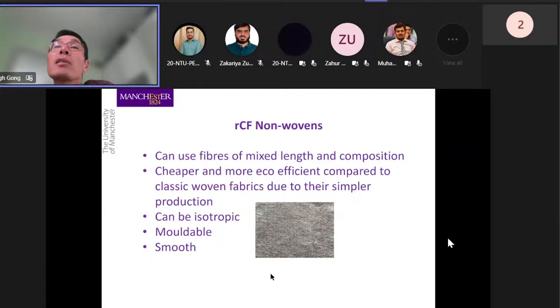And the processes of nonwovens tend to be much cheaper compared with traditional textile processes, things like weaving, because if you are going to do weaving, obviously you need yarns or filaments, where of course recycled carbon fibers are short and random. And the other thing with nonwovens is if you do the process properly, you can control the fiber orientation in a random way, so you can achieve an isotropic structure. Mainly, it's two-dimensional. It's difficult to do 3D isotropic structures, but 2D, yes. And the product is also moldable, so you can make them into a 3D shape.